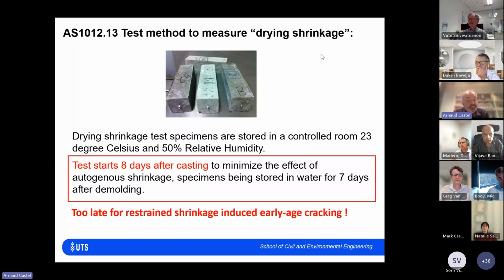It would be easy to fix. It's just about changing the standard and saying we start measuring after 24 hours, and we change the name from drying shrinkage to total shrinkage. But at the moment, it's not. I agree with what Greg just said. It's not really useful to control early age cracking because we're measuring a long-term shrinkage. So that's the first problem with what is available to engineers at the moment.